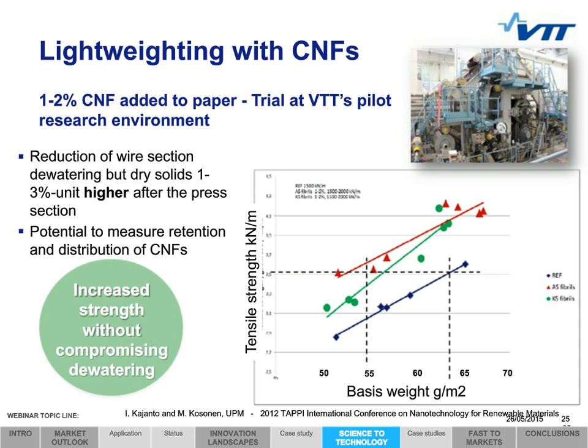The graph in this slide shows development of tensile strength of paper as a function of basis weight. The reference trial points are marked with blue, and the trial points in which cellulose nanofibrils have been added with red and green. With the CNF addition, it was possible to reduce the basis weight by 8 grams per square meter while maintaining the tensile strength at the previous level. In our pilot environment, we also have tools to monitor the retention and distribution of cellulose nanofibrils in the web.